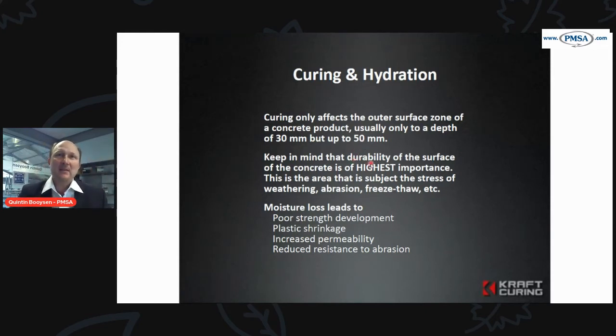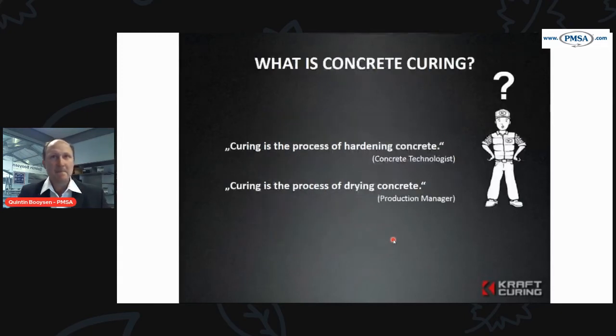However, keep in mind that the durability of the surface of the concrete is of the highest importance. This is the area that is subject to the stresses, the weathering, the abrasion, so the paver, the abrasion on the outside on concrete columns, the freeze thaw, or even just to protect the steel that you don't want to lose. You want to have the highest possible strength on the outside of your concrete. Moisture loss leads to poor strength development, plastic shrinkage, increased permeability, and reduced resistance to abrasion. So you end up with a weaker concrete on the outside, more porous.